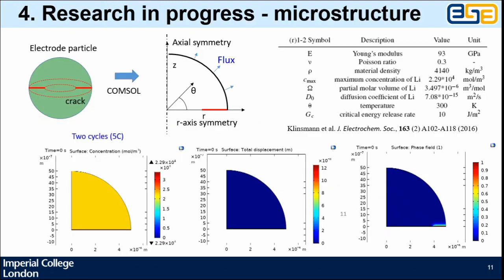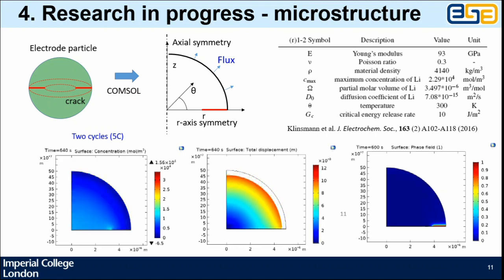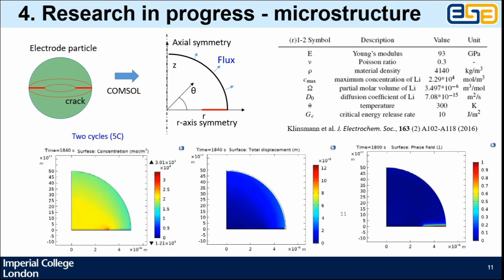In the next few slides, I would like to introduce the research in progress in our group. We are studying the microstructure of the electrode particle and the effects on the cracking behavior. We built a 3D model in COMSOL using the axial symmetry. At the bottom, we get the results of lithium concentration, displacement, and crack propagating by phase field. This is an early-stage result, and in future we will consider more complex geometry.